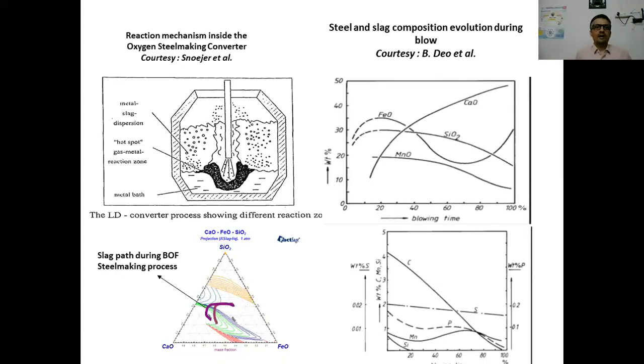If I'm talking about the LD steel making process, this is the schematic diagram of the LD steel making process, where liquid pig iron, which is coming from the blast furnace, is blown with a high velocity oxygen jet, and the objective is to do the refining. That means to remove the impurities present like carbon, manganese, silicon, phosphorus. All these impurities are being oxidized, and then they are being combined with the flux that is being added during the process. The process also involves a lot of oxidation reactions which are exothermic in nature, so they also help to dissolve the scrap and other coolants.